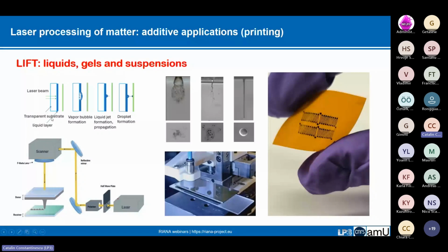In here we have a sequence which illustrates how a bubble forms, how the jet follows, and how the droplet is landing. So these are the key stages in governing resolution and stability. And the simple setup of LIFT really helps a lot to control this properly. So here you have the schematic, and here you have the actual image of the donor, this glass slide, which is covered in silver nanoparticle based ink, which was made by spin coating because it was highly fluid, and the receiver, which is also a glass slide in this case, but we can change it with a different material.